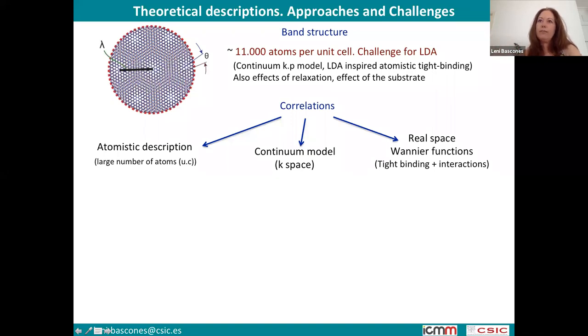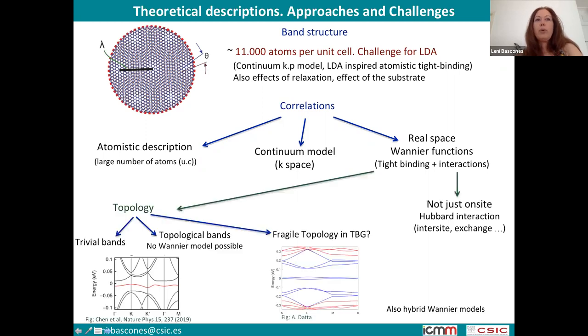So you would like to have this kind of tight-binding plus interactions model, like the Hubbard model, like, for example, we have used a lot in cuprates or in iron superconductors, or models similar to the ones of the heavy fermions. And here there has been another issue which has come to complicate our lives, which is topology. In general, all these systems are described by taking the bands for each of the valleys of graphene. And in particular, there can be two situations. One is that the bands are called trivial, in the sense that they are not topological, and so we can build a model based on Wannier functions for this system.